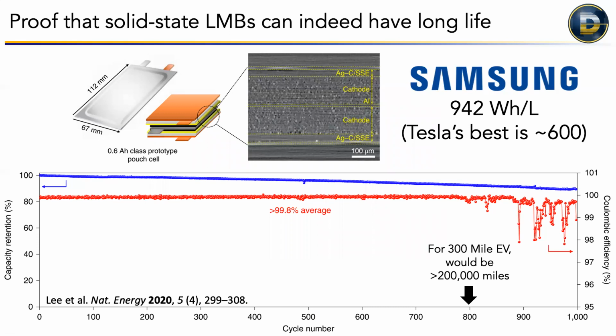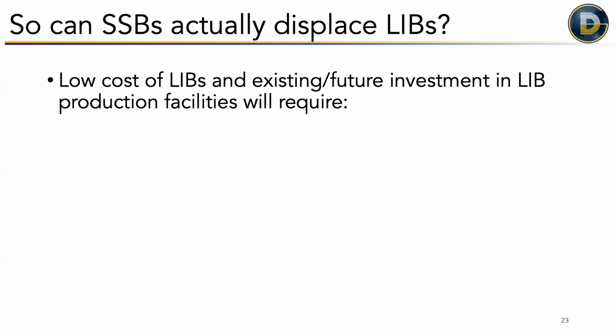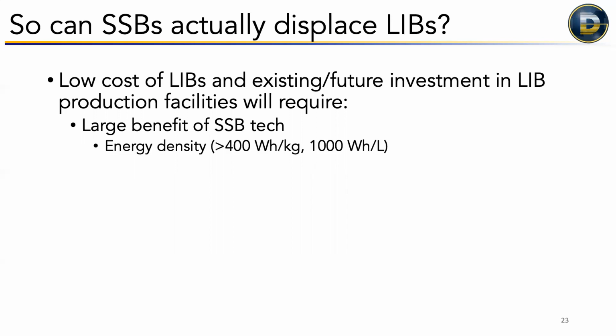But will this actually happen? Can solid-state lithium metal batteries displace lithium-ion? Because we've seen how much the lithium-ion batteries have come down in cost. They're gaining a ton of momentum. So how could it actually displace lithium-ion batteries? Well, there has to be a big benefit of solid-state batteries, namely really high energy density. And this isn't just like a 5% or 10% improvement. It needs to be a step change, so 25, 30, 50% higher energy density to motivate this shift.